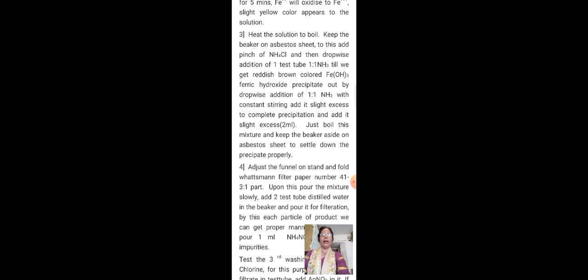To this, add a pinch of ammonium chloride. Often it is given as 1 or 2 grams, but that much is not necessary because we are using it only as a reagent. While using it, chloride should not remain in the solution, as it will increase the weight, which is not proper for us. So only a pinch, as a reagent, should be added.